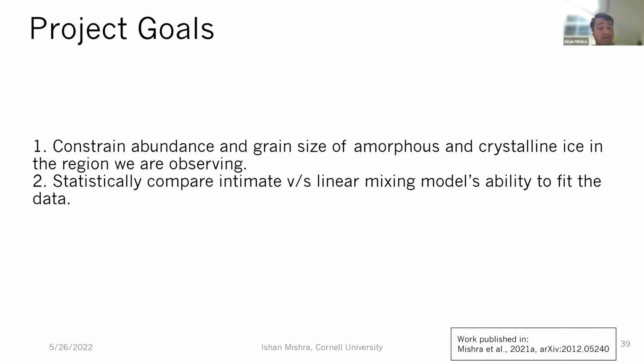So in this area there is some water, in this area there is more salts, and in this area there's something else. When you're looking at the total reflectance from that area, it can be approximated as a linear sum of the reflectance of the individual species weighted by how much their area is. That is a linear mixing model. These two different models basically correspond to two different physical states of the surface material you're seeing, and we wanted to see which one is preferred.